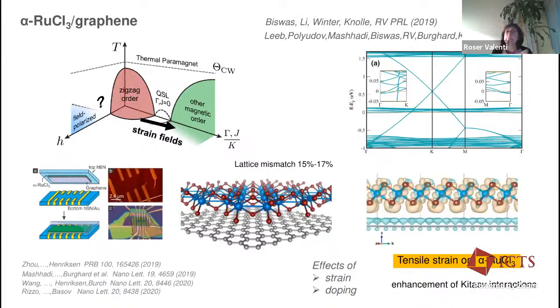The last slide is the work we have been doing with Johannes Knoller. Another way of manipulating your ruthenium trichloride is by creating heterostructures with graphene. Because there is a strong mismatch, alpha ruthenium trichloride will try to adapt to this graphene lattice. So we expect effects of strain as well as doping. And in fact, there is an important charge transfer, as can be seen in calculations, from the graphene layer to the alpha ruthenium trichloride, so that the graphene layer gets hole doped, as can be seen here.